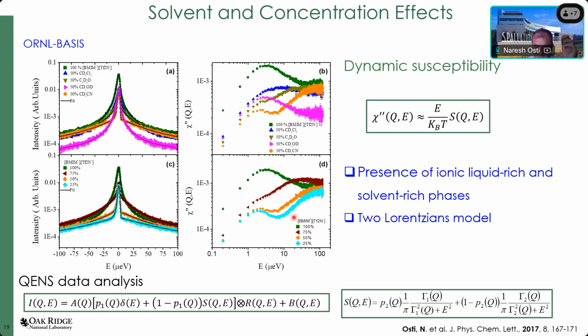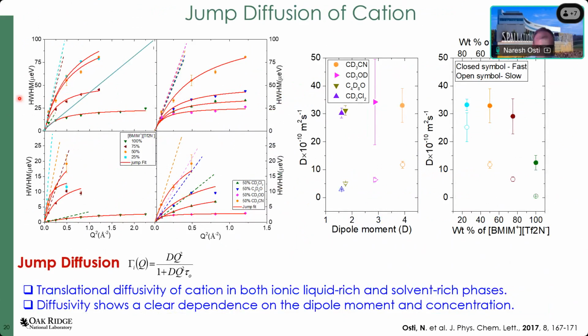Therefore, in order to capture the dynamics of those two processes, we use a sum of two Lorentzians, from which we extracted the half width at half maximum. Here is the Q dependence of those half widths. I'm not going to go into detail, but similarly as before, we extracted the diffusion coefficient and plotted it as a function of the dipole moment. As you can see, this is the slow process.